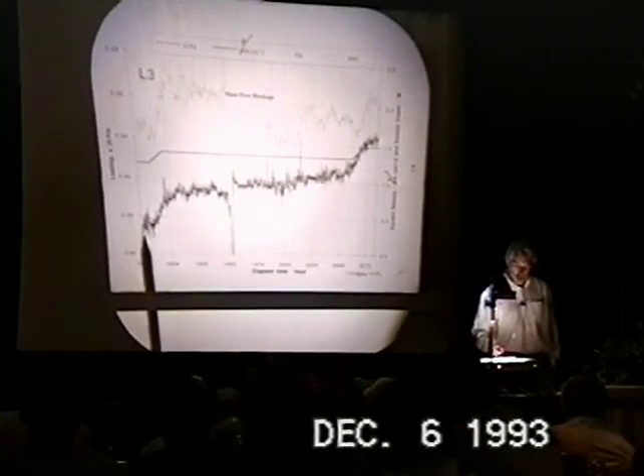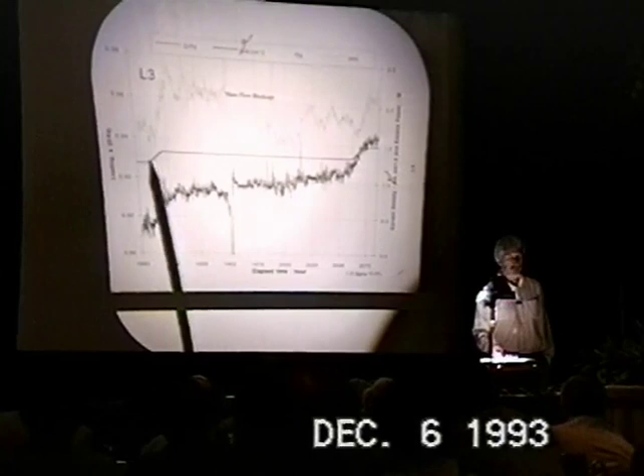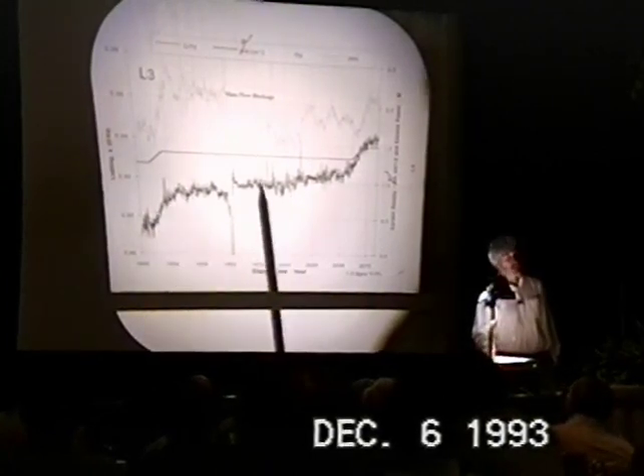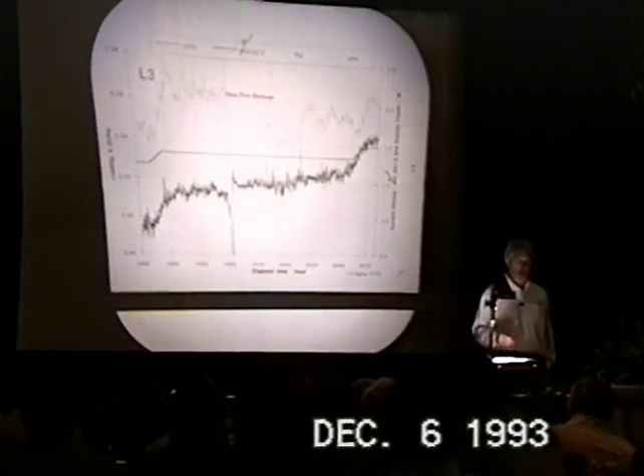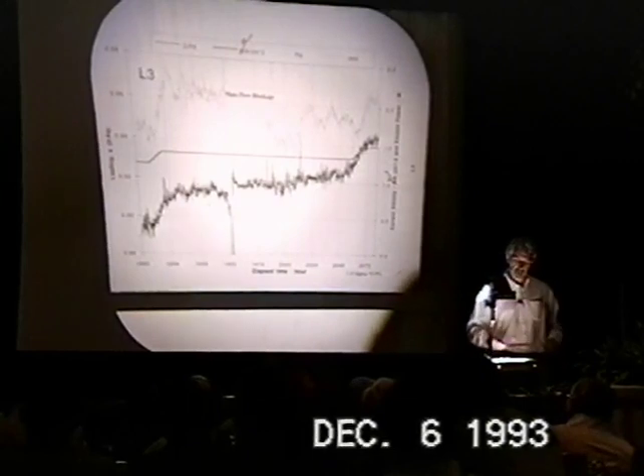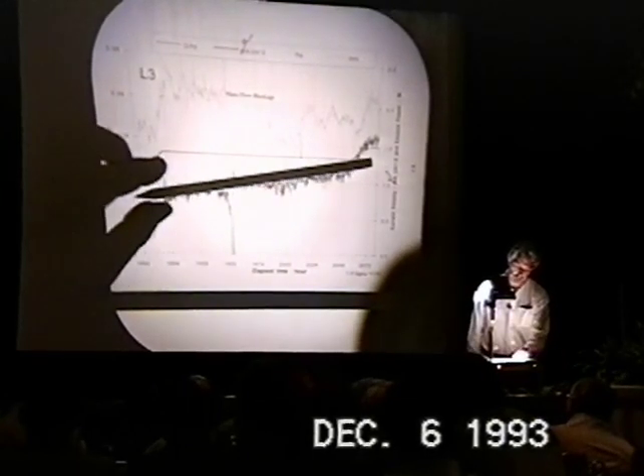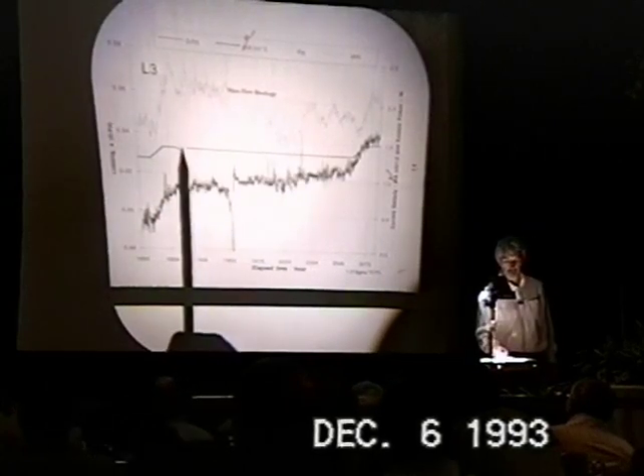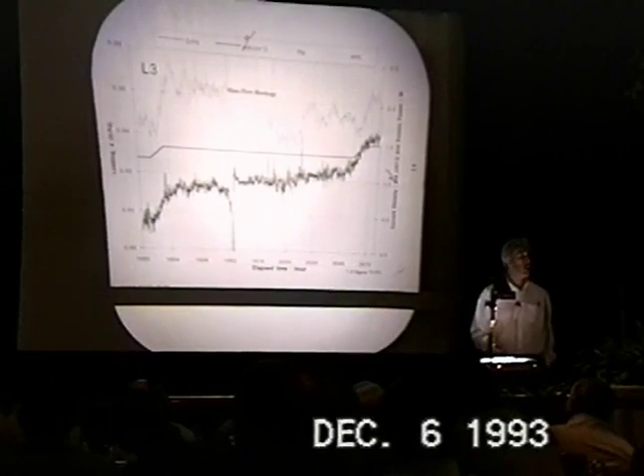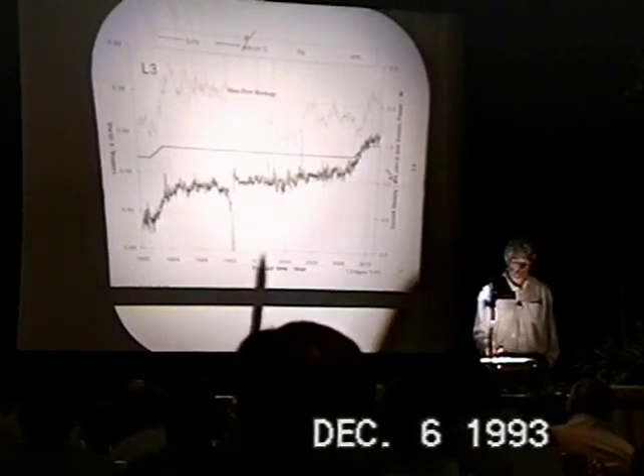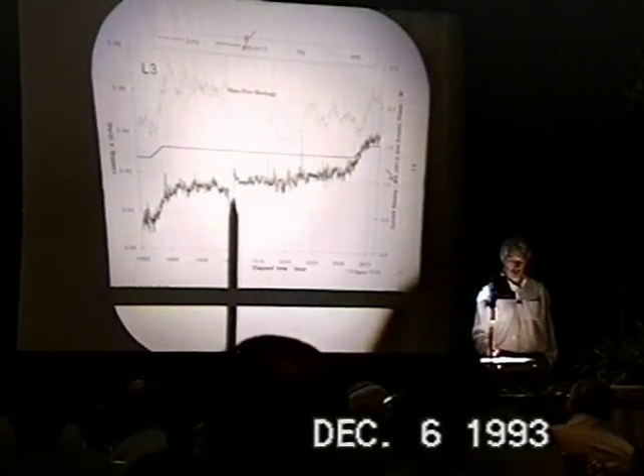The current density was increased. The loading increases with the increasing current density in the way that it typically does. It responds to the ramp and then continues to increase for a considerable period of time after the current density ramp is finished. In this case, the loading seems to be more or less spontaneously increasing by itself at a time of constant current input. This is the region of time that I just discussed.